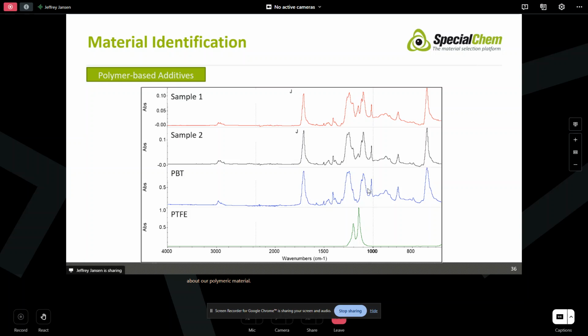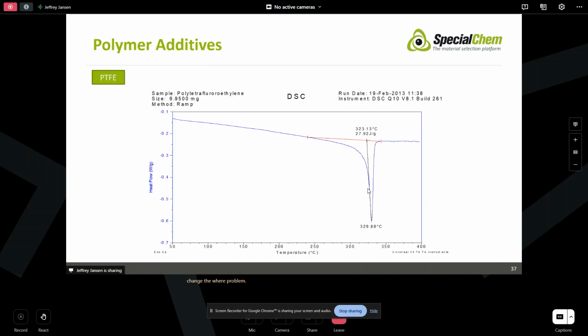So we can also understand some things about polymer-based additives. Here we have some samples. Sample 1, sample 2, both are based upon PBT, again, by the FTIR. But we also see some additional absorption bands that are suggestive of PTFE, polytetrafluoroethylene, which is commonly added to polymeric materials to change the lubricity, the coefficient of friction, and the wear properties.